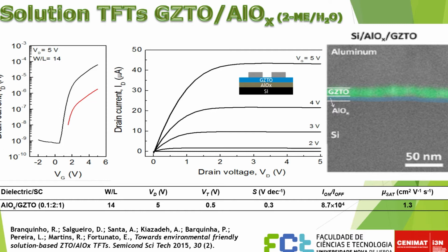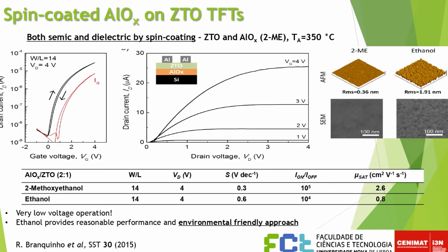So here you can see the aluminum oxide is the blue layer, very, very thin. This is 50 nanometers. And also the case where we combine aluminum oxide with ZTO TFTs. Of course, here we still have some limitations in terms of the mobility, but we will see in some of the next presentations from our group that we can already improve these values a lot.